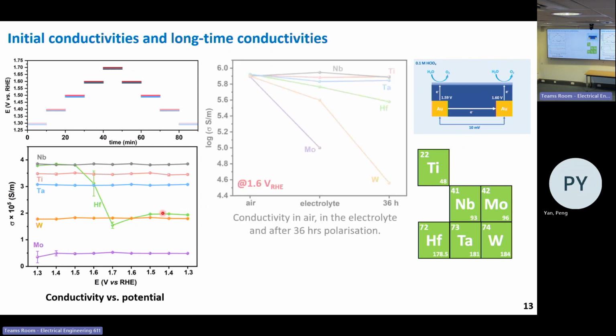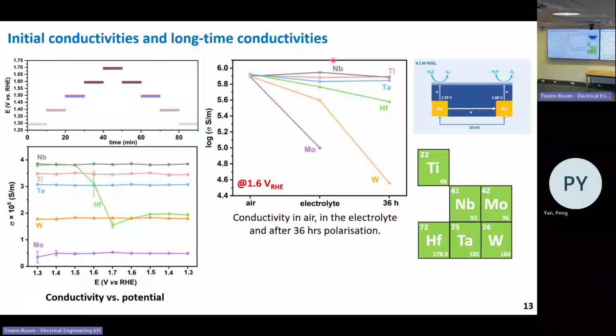In terms of the long time stability, titanium, niobium, and tantalum remain conductive and stable even after 36 hours of polarization, while the oxide layer went deeper on hafnium and tungsten.